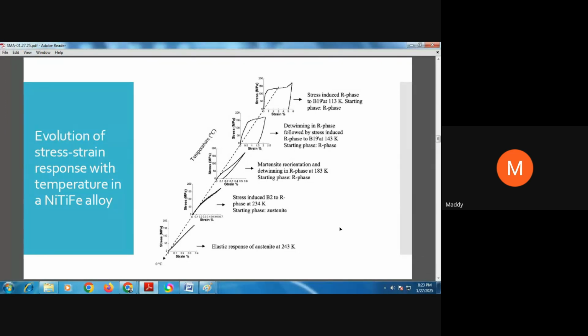Now, as you cool it a bit further, you are in a phase where the starting phase is R phase. So when you apply stress, the R phase detwins, and then the martensite starts reorienting. That is why you are seeing some unrecovered strain here. Now, this unrecovered strain can be recovered by heating the material.